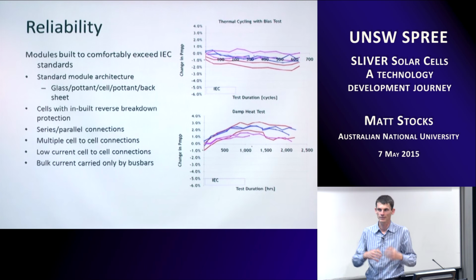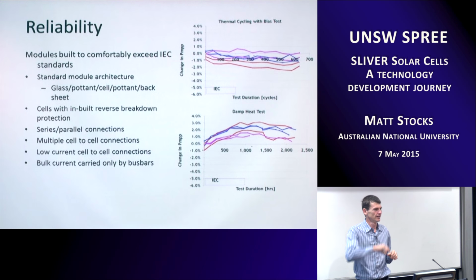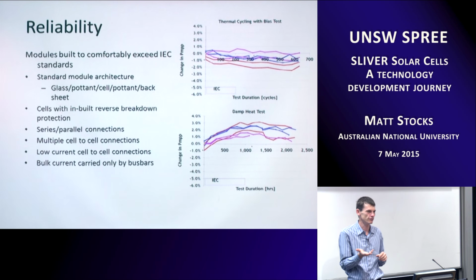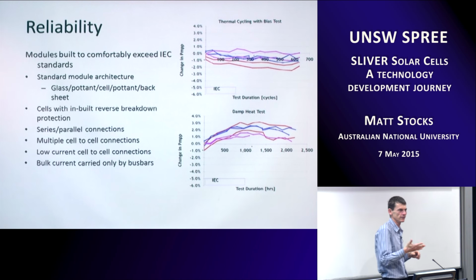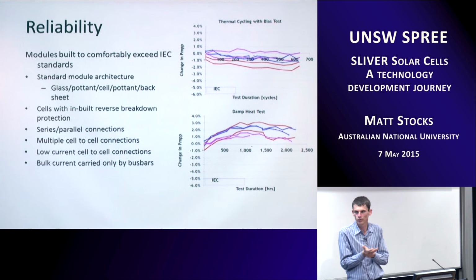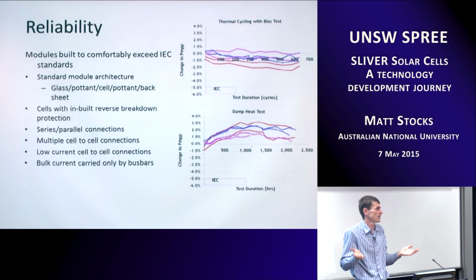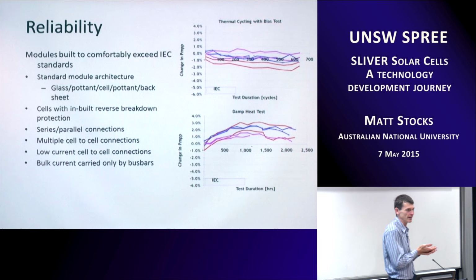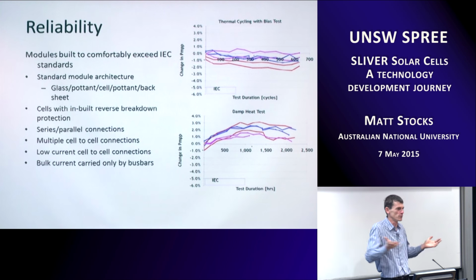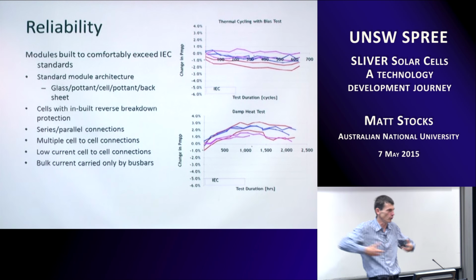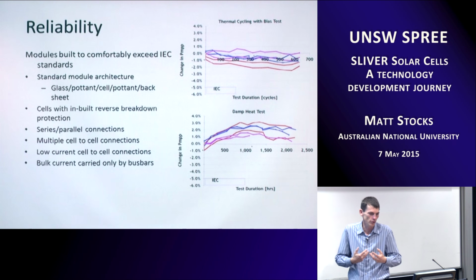So the subassembly that was being passed, that was our core building block. If you turn it over, what you'll notice is that it doesn't look the same on both sides. One side it kind of looks like it's out of focus. So one side, what we've got is fiberglass. There's crane glass, which is our substrate that we built all of our subassemblies on. So we're placing all these cells on this fiberglass shim, and that was okay because that fiberglass shim was actually being put in modules by people. People are having problems with cells cracking. We're putting that in there to avoid the thermal expansion inside the module. So it was actually helping control the expansion and contraction of the module.